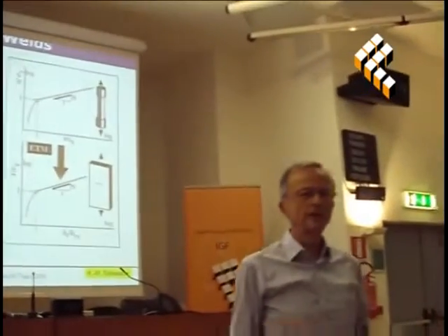Now you may question the sense of a power law equation. Again, this is a model. You can draw power laws with any kind of stress strain data. It's always possible. You do a fit, and then you have continuously hardening materials. It is relatively easy. It is questionable when you have a steel with a long Lüders plateau. Then you have to find something else.